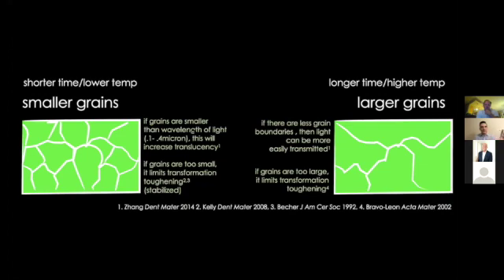If somebody says, oh, my zirconia didn't have the desired properties, is it going too long, or is it too hot, or is it too short? It's just really hard to know exactly what's happening with the microstructure. But the thing I think is the most important is following the manufacturer's recommendations for the sintering time and the sintering temperature, because as I try to summarize 4 studies here, the studies don't totally agree, and we don't really know what's happening when we grow grains to different sizes, or by sintering at different temperatures and times.